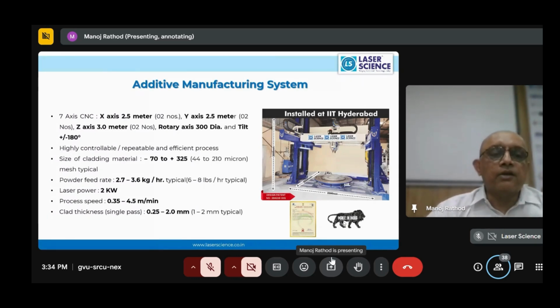Laser, we have used 2 kilowatt lasers. We have used a 2 kilowatt, 2 laser system with a beam switch, and the process speed is 0.35 to 4.5 meters per minute. So this is a very high processing speed, and cladding thickness you can also vary from 0.25 to 2 millimeters. So this is a unique, first of its kind, largest size laser system we have built, and we are proud to hold the patent of this product.